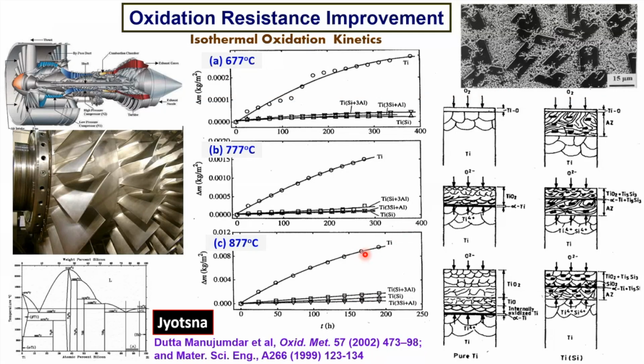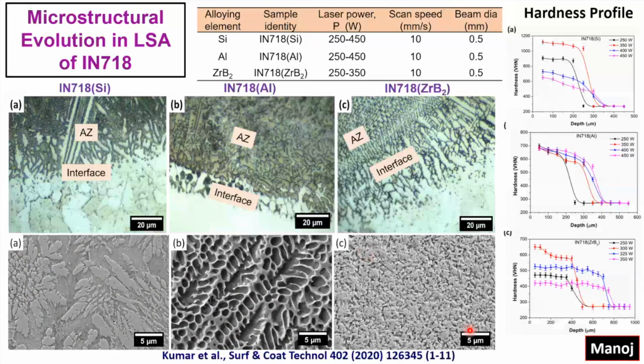So borrowing from this clue, Manoj again tried to alloy silicon, aluminium, or zirconium diboride onto Inconel 718. And so this is the cross-sectional microstructure, and this is the top microstructure.